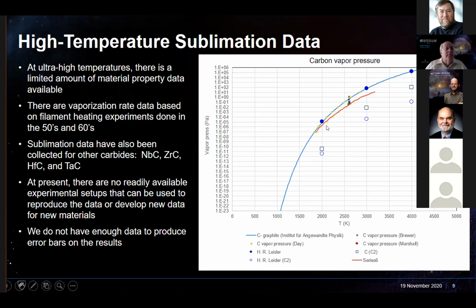The ones that are seriously low are where people were looking at carbon coming off as carbon, but it's also coming off as C2. The lines down here are for C2, and those are coming off at a much lower rate than carbon, so they're just up there in the plot. But you have some flexibility or variation in here that is at least in the order of magnitude range, and it may be higher, and again it's getting worse as you get higher.